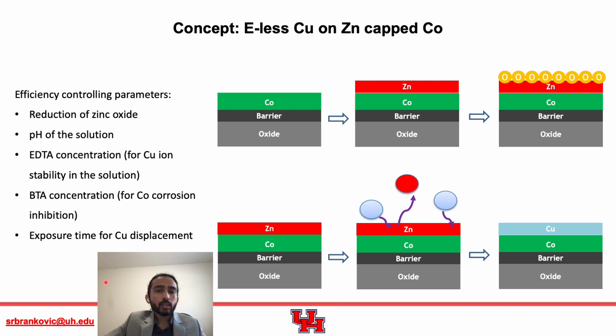All of these experiments are optimized at a pH of 5 and 6. So the copper stability at near neutral pH is not that good, and that's why we are introducing EDTA complex, which can form complex with copper ions and prevents copper hydroxide precipitation in the aqueous-based solution.